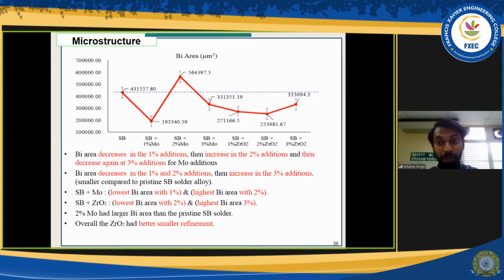Supposedly when they are at the interfacial layer, they produce a thinner IMC layer, which was compatible in this study. From that, I could prove my hypothesis that the nanoparticles, especially for the 2% molybdenum, were not much found in the microstructure or the solder side to reduce the Bi area, but were mostly found at the interfacial side, which reduces the IMC thickness. However, although this gives a good impression on the IMC layer thickness, the hardness properties will not be as good as the shear strength. We need to be satisfied in terms of both shear strength and also hardness.